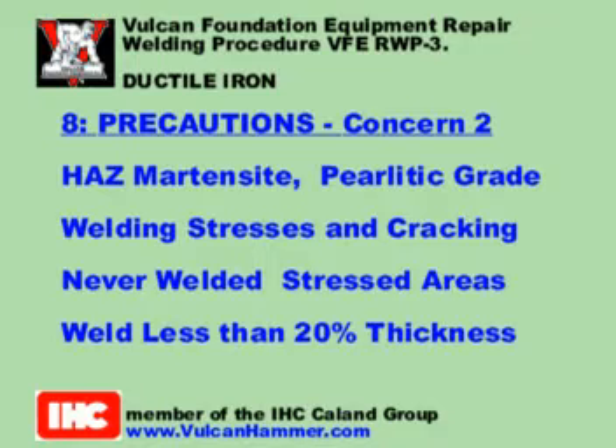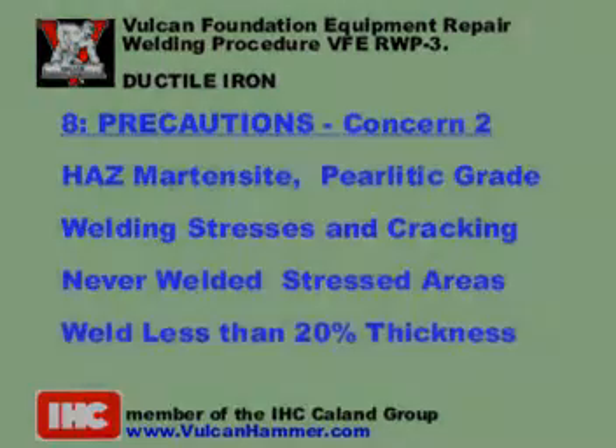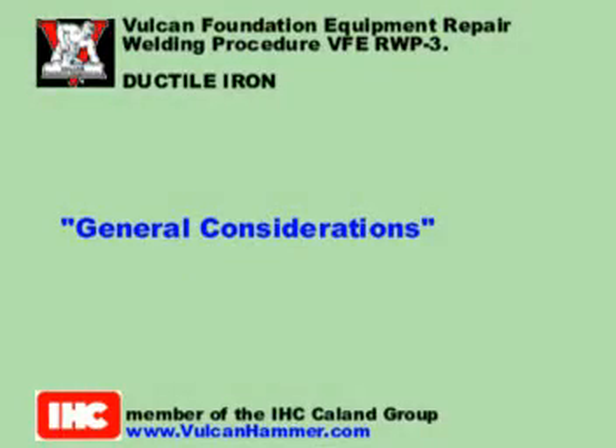Concern 2. The HAZ will produce a martensite, especially in the pearlite grade, which must be tempered to restore any ductility. Ductile iron is more susceptible to welding stresses, and more likely to crack while welding or during cooling. Therefore, ductile iron should never be welded in highly stressed parts or areas. Welds should never be made when the weld is more than 20% of the metal thickness. See also the section on general considerations for more information.